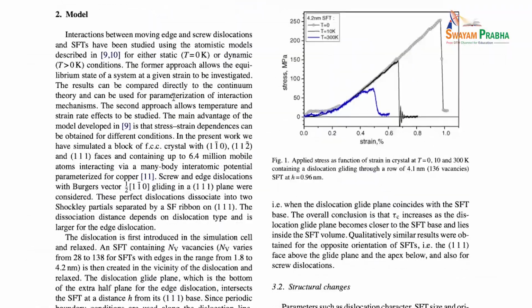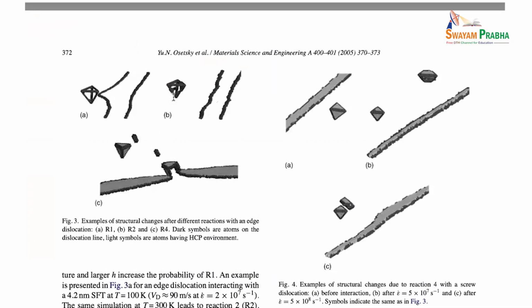Anyway. In this paper, this was MD back in the days. By hand, we created these stacking fault tetrahedra. We created triangular vacancy loops, let them relax, and they form these tetrahedra. In gray here, you have stacking faults, and the edges here are the Lomer-Cottrell locks. Then in the same simulation, we add a dislocation, and we apply a stress to force the dislocation to interact with the stacking fault tetrahedra and see what happens.